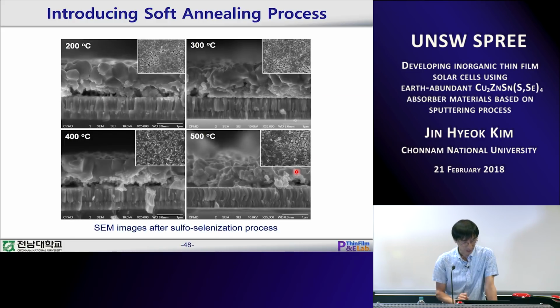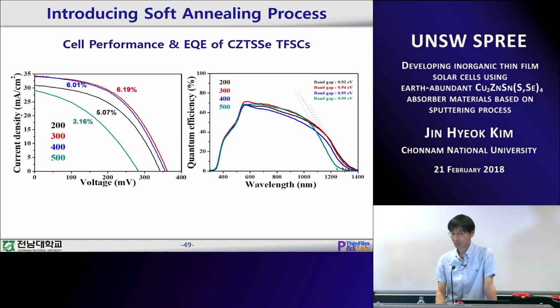Okay, this is the result: the cross-sectional SEM images of the cell structure after sulfo-selenization. We just observed the absorber material, and we cannot see a big difference in the samples pre-annealed at 200, 300, and 400. But in the 500 sample, the morphology becomes much worse. We also made a thin film solar cell using this absorber layer, and we get this result.